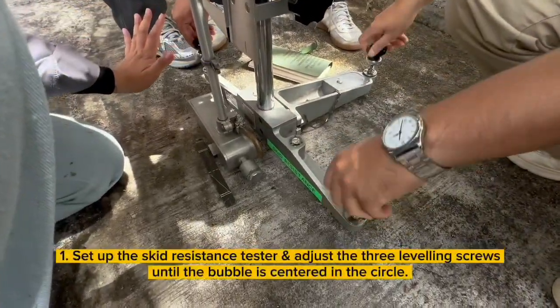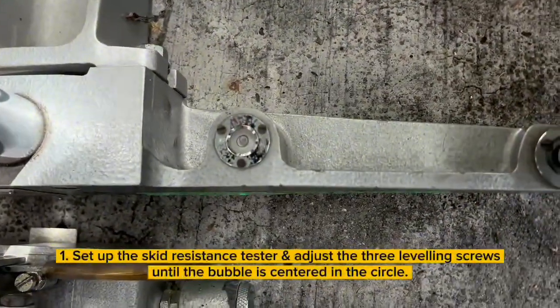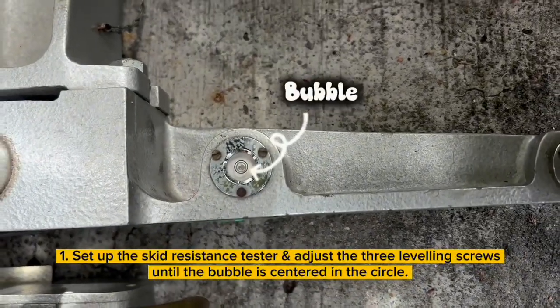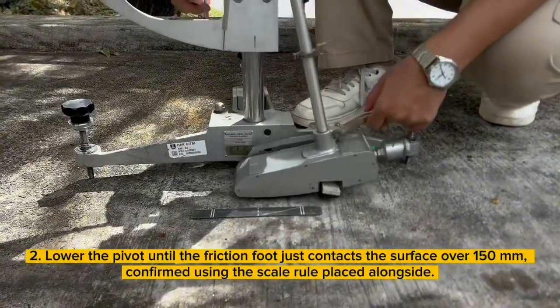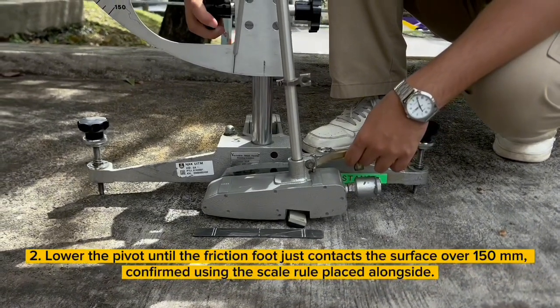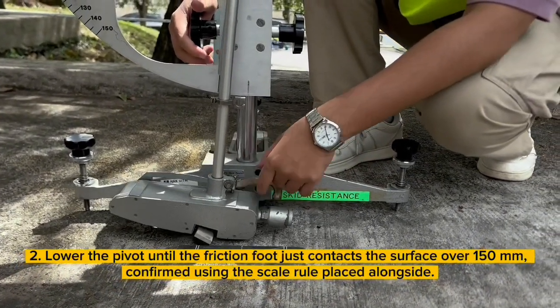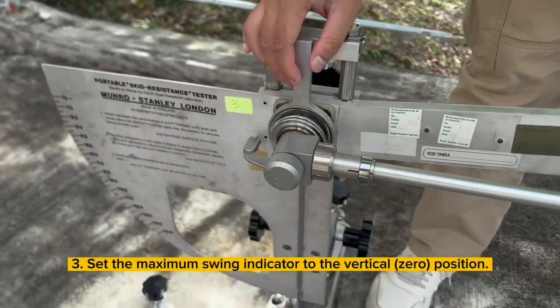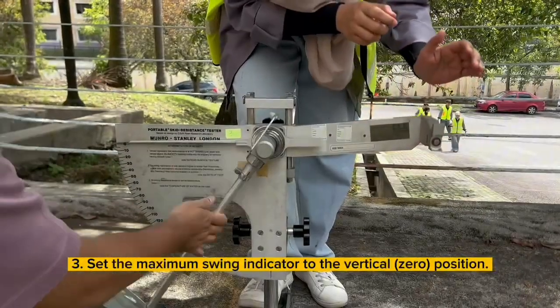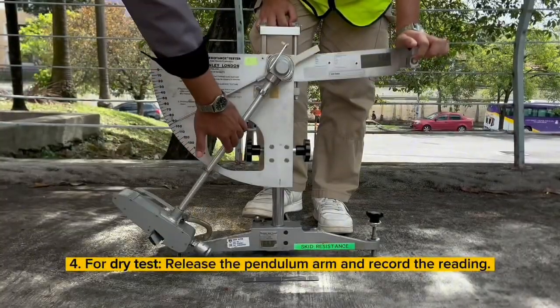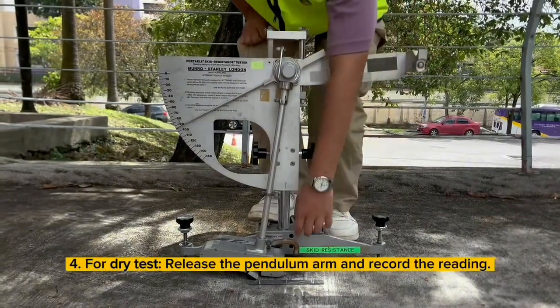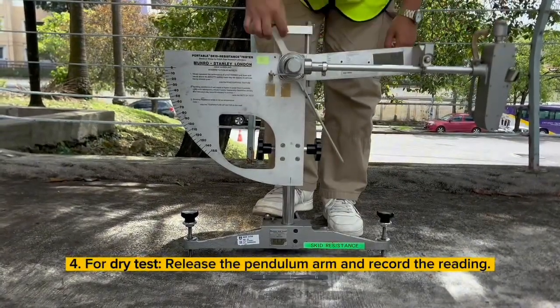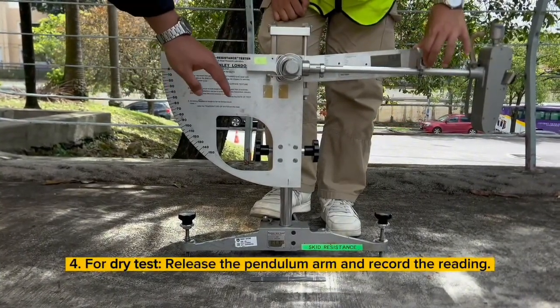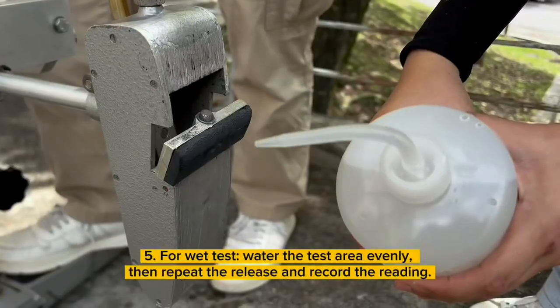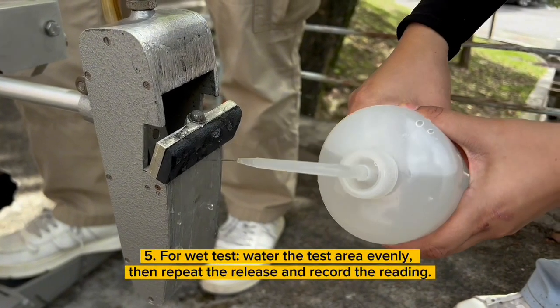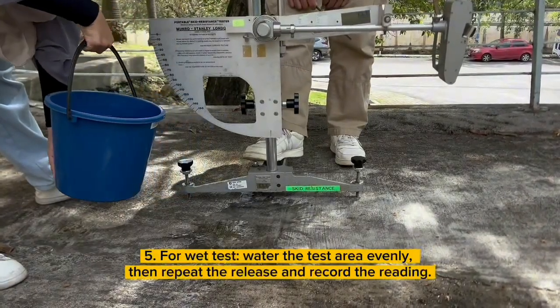Next, for the procedure, firstly, set up the skid resistance tester and adjust the 3 leveling screws until the bubble is centered in the circle. Next, lower the pivot until the friction foot just contacts the surface over 150 mm. Confirm using the scale rule. Next, set the maximum swing indicator to the vertical 0 position for calibration. For the dry test, release the pendulum arm and record the reading. Next, for the wet test, water the test area evenly, then repeat the release and record the reading.